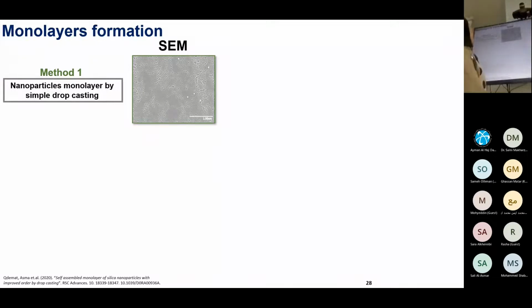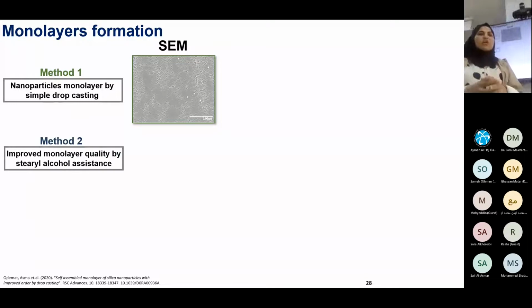By this method, I end up with a monolayer which is not uniform or homogeneous over the whole silicon wafer, where some areas are not covered with the particle, some have multilayers, and some have grains, which come maybe due to the surface tension, which leads to the contraction of the particle grains during the drying. But somehow, with this particle and with this good size distribution, we could find some good areas with a good degree of ordering.